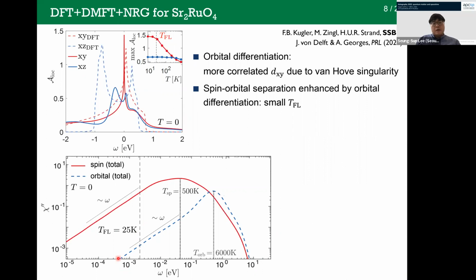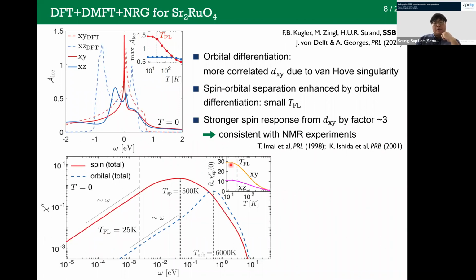Both curves become linear in omega, which is the characteristic of the Fermi liquid scale. So we found that the interplay of spin orbital separation and orbital differentiation led to this smallness of the Fermi liquid scale. And we also studied the orbital dependent spin responses, and we found that the XY orbital had a stronger response than the other two orbitals by roughly a factor of 3, which is also consistent with the NMR experiment. So let me conclude this first part of my talk.